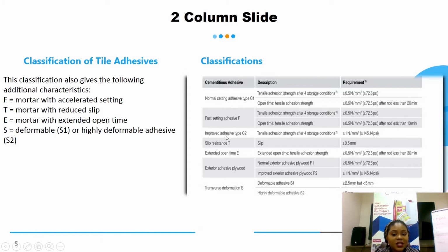So for improved adhesive type C2, we have a tensile strength of greater than or equal to 1 Newton per millimeter square, which is what you should be looking out for when you're tiling for high rise. Greater than or equal to 1 Newton per millimeter square. This could be up to 1.5 Newton per millimeter square, or even 2 Newton per millimeter square. What you should be looking at is to make sure that the tile adhesive you're selecting is C2.